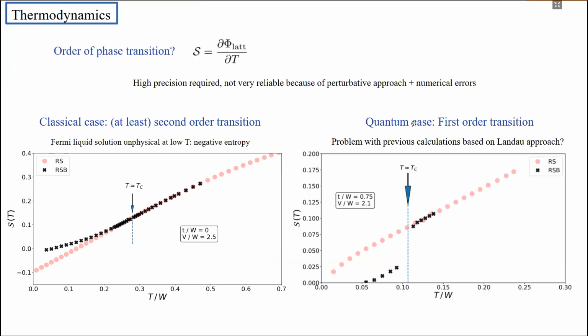Okay, and then there is one last thing that I would like to mention, and this is that we can even take a closer look at the order of the phase transition with our method. In particular, we can evaluate the free energy density of our original Hamiltonian. And by taking the derivative of this free energy density with respect to the temperature, we can evaluate the entropy of the system. And we can examine the temperature dependence of this entropy. Now, what I should mention is that you should take these results with a grain of salt because very high precision is required for these calculations. And now we are relying on a perturbative approach. So of course, we can never be absolutely sure about our conclusions, but nevertheless, this is what we get.